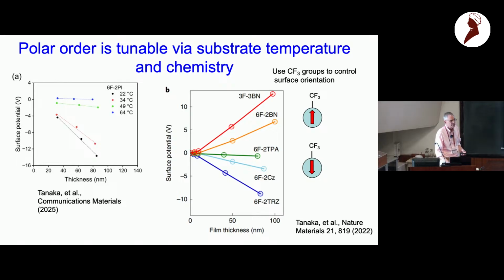So it forms a template from which then the rest is kind of growing in a way in terms of the dipole alignment. No, it's not a template. I mean, well, you can say the interface is a template. Yeah. Yes. Yeah. But the material below is not a template. So if you change the temperature in the middle of the deposition, you change to a different degree of alignment, because it's controlled by the free surface at that new temperature. Okay? All right.